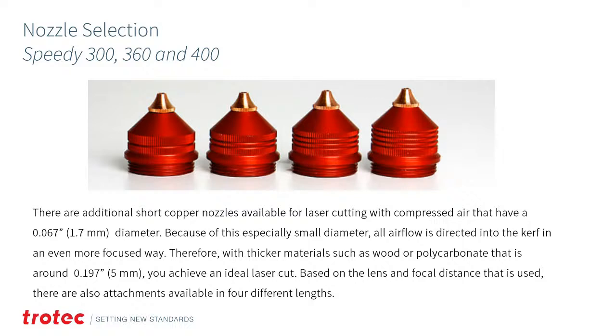I get some really neat effects and it really blasts that air down. I was cutting some quarter-inch sheet stock plywood the other day, cutting puzzles, and I was getting a lot of residue on the surface and I can't really wipe it off because it was raw wood. I switched to this cone and it dropped the amount of residue on the surface of that plywood by about 80%, just going from the standard small mouth cone to the high pressure nozzle, because it forces that smoke down through the cut versus out of the top, so you get a cleaner cut.